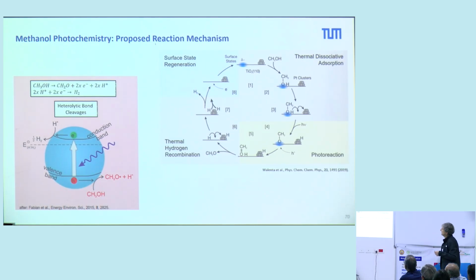And here is a cycle we propose. We have our titanium oxide surface, we have these BBO sites. In the first step, the methanol is reacting with these BBO sites, and you are producing a methoxy or alkoxy. And then, if you shine in light, you produce holes, and these holes oxidize this methoxy and form aldehyde. And then this aldehyde has to thermally desorb from this reactive site.